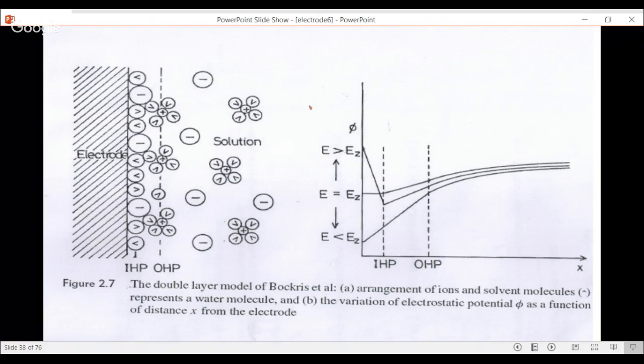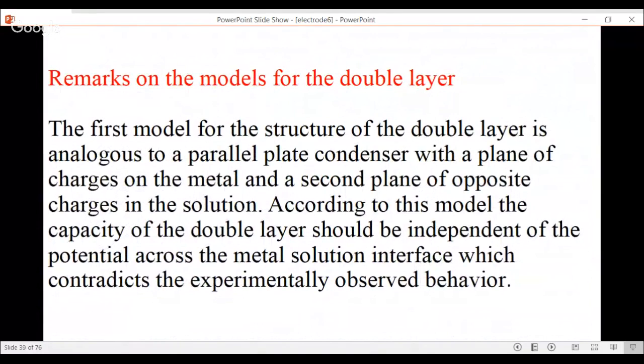All these models are only for the metal solution interface. We have not yet gone to any other thing. In the metal solution interface, how the ions are arranged in the solution phase. The first model for the structure of the double layer is analogous to a parallel plate condenser with a plane of charges on the metal and a second plane of opposite charges in the solution. According to this model, the capacity of the double layer should be independent of the potential across the metal solution interface, which contradicts the experimentally observed behavior. It should be constant with respect to potential, but it is not so.